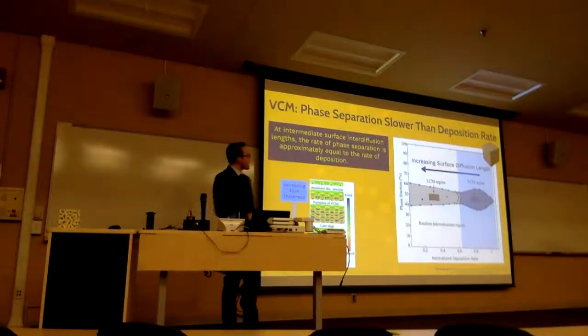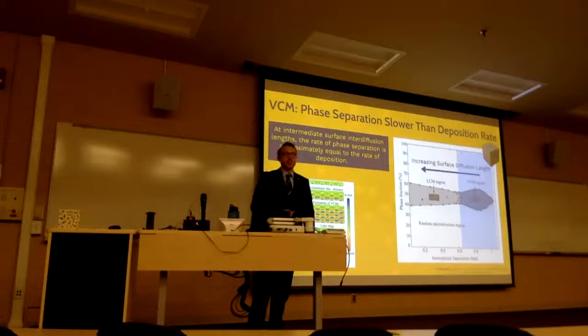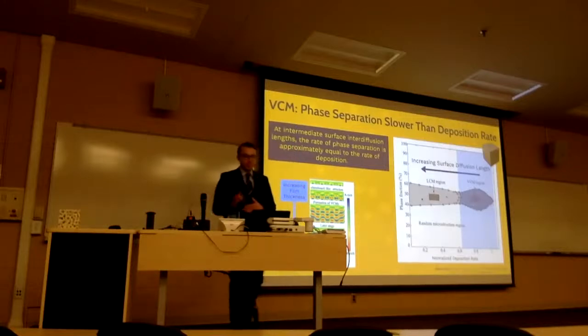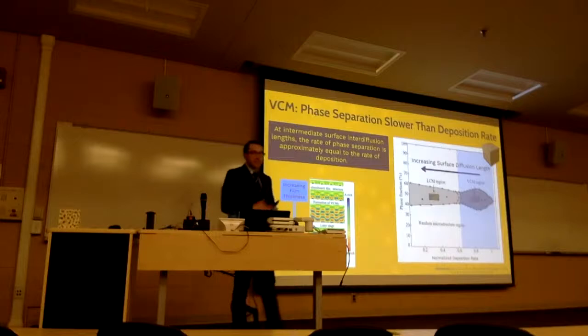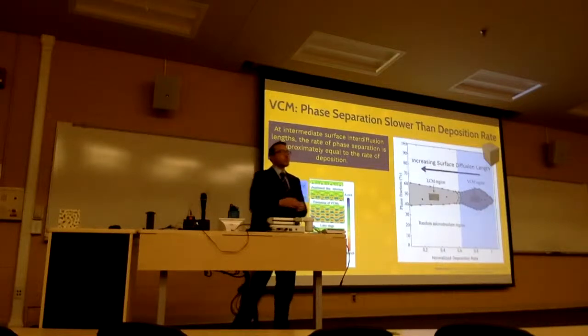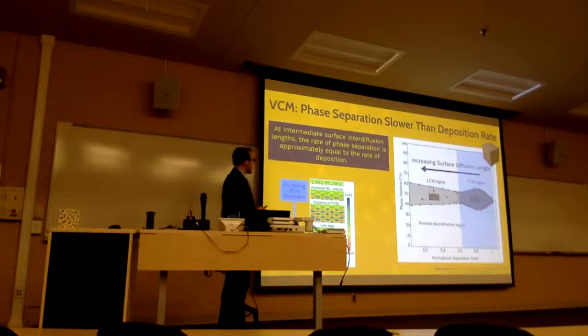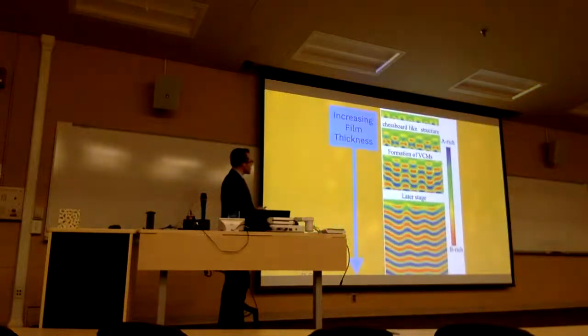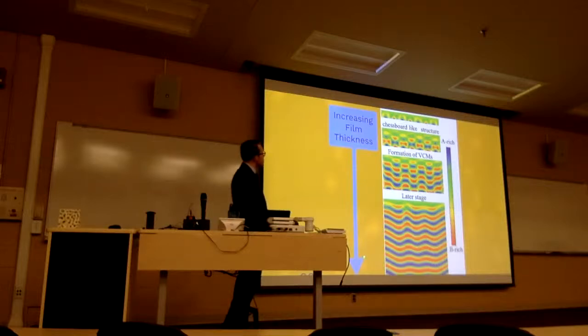Now, at slightly lower diffusion length, we see a transition in phase separation direction to the VCM structure. What's happening here is that the rate of phase separation is roughly equivalent to the deposition rate. And so looking at that more closely, what we predict is happening is this is describing increasing film thickness as you go down the page here.